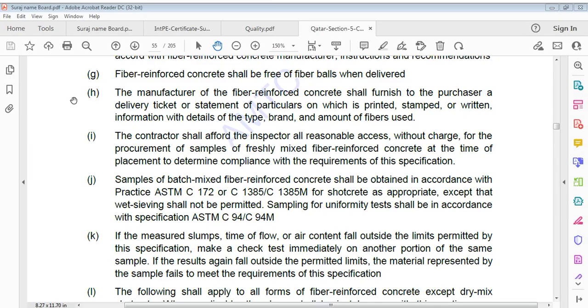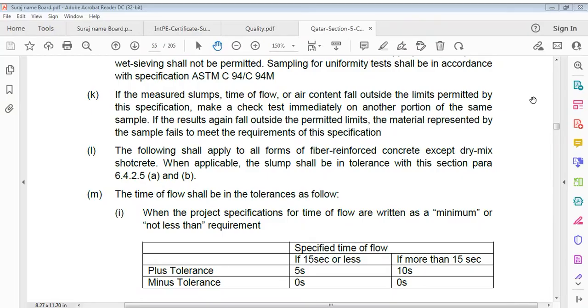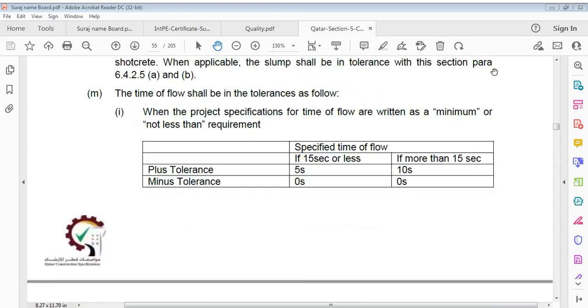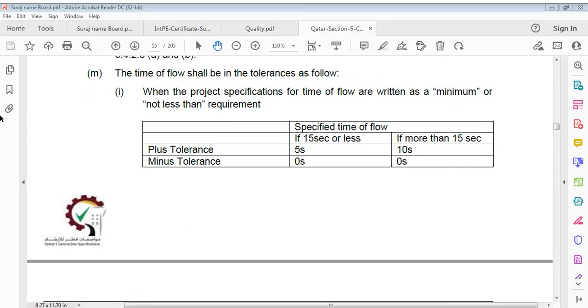Sampling for uniformity tests shall be made. If results fall outside limits permitted by this specification, make a check test immediately on another portion of same sample. If results again fall outside permitted limits, material represented by samples fails to meet requirements. Following shall apply to all forms of fiber reinforced concrete except dry mix shotcrete. Time of flow shall be in tolerance as follows: when project specifications for time of flow are written as minimum or not less than requirement, plus tolerance: if 15 seconds or less, 5s; if more than 15 seconds, 10s. Minus tolerance: 0s, 0s.